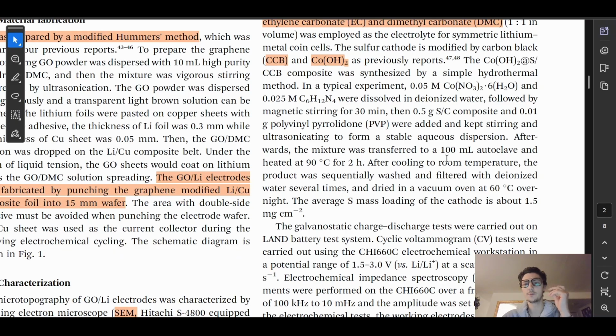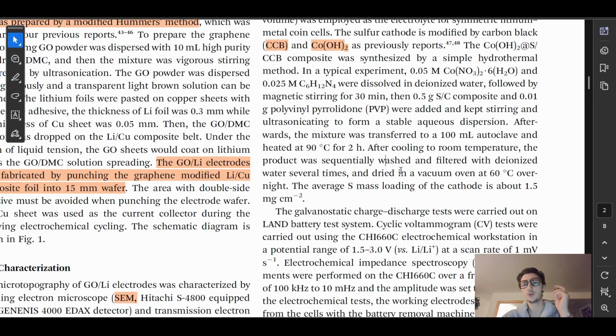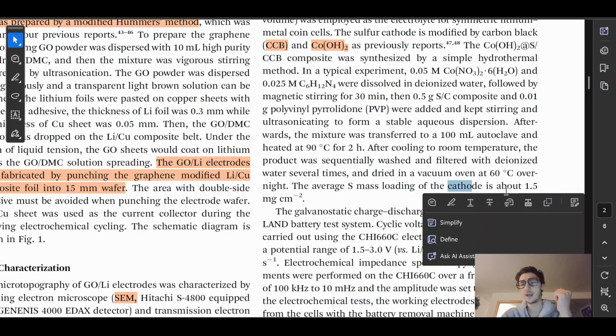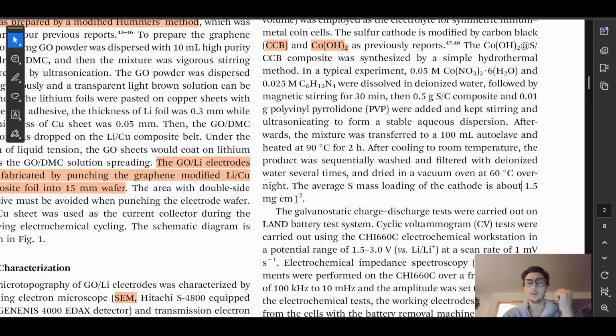Afterwards, the mixture was transferred to a 100 milliliter autoclave and heated at 90 degrees Celsius for 2 hours. After cooling to room temperature, the product was sequentially washed and filtered with deionized water several times and dried in a vacuum oven at 60 degrees Celsius overnight. The average S, I'm assuming S means sulfur here, mass loading of the cathode is about 1.5 milligrams per centimeter squared.